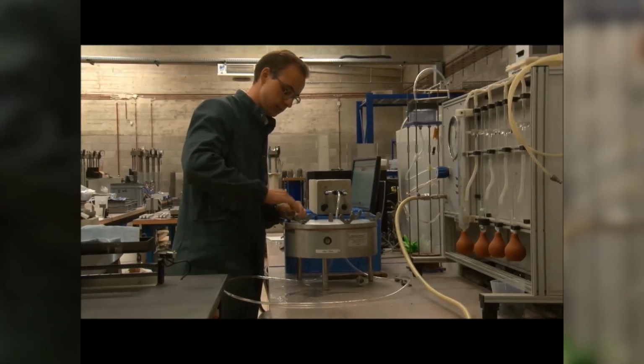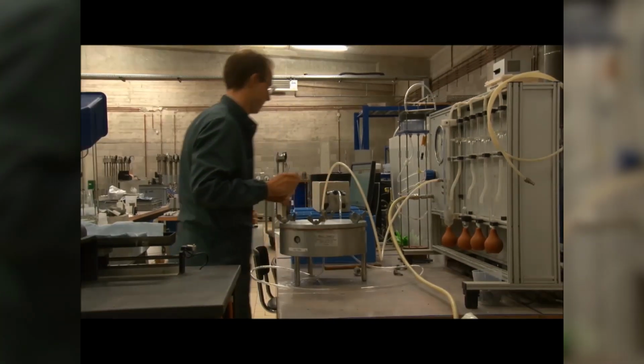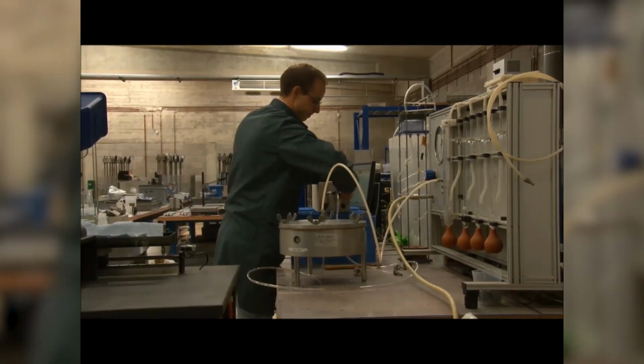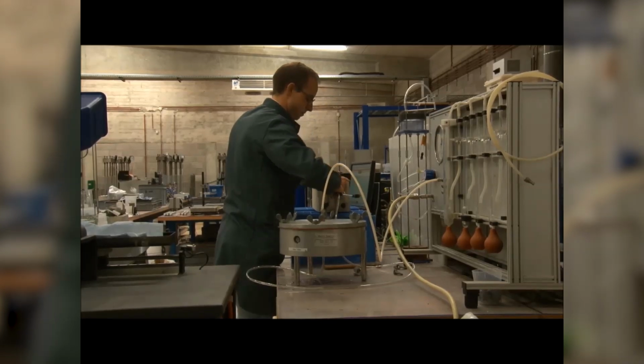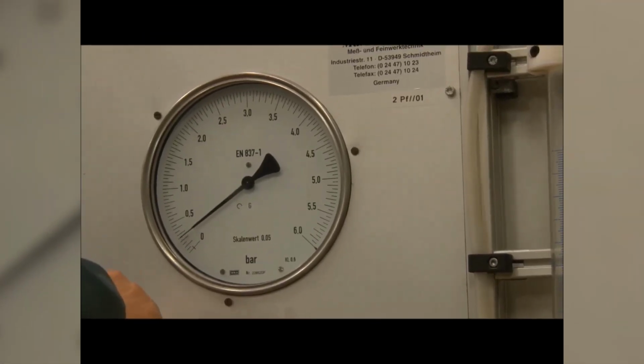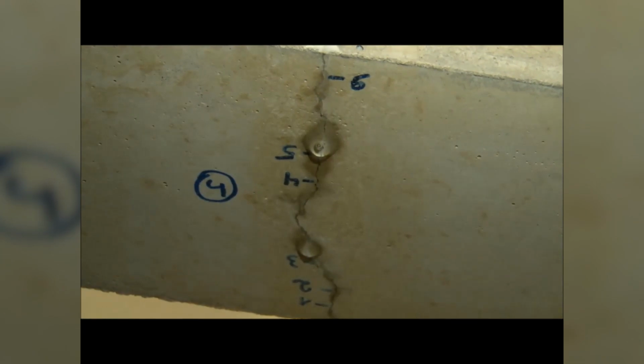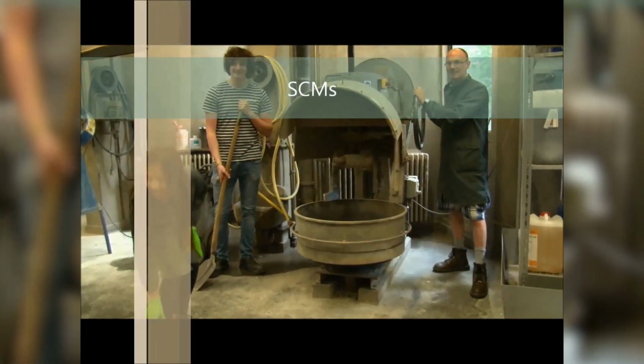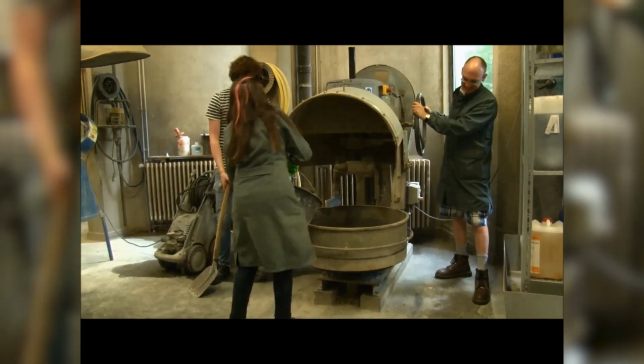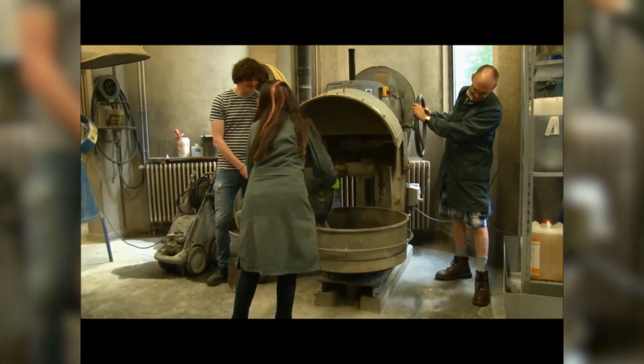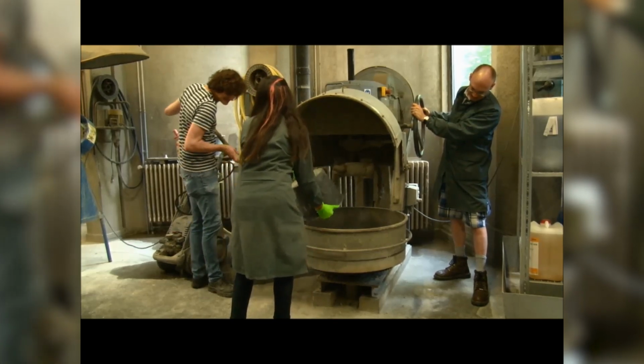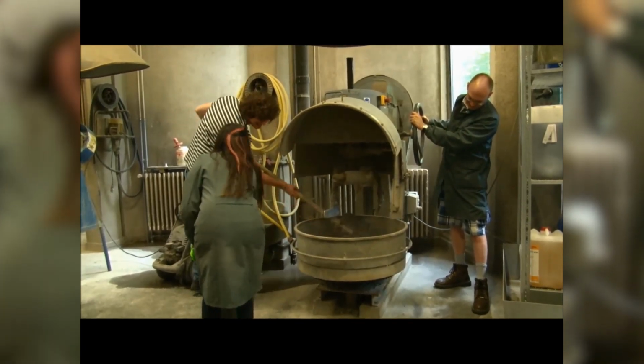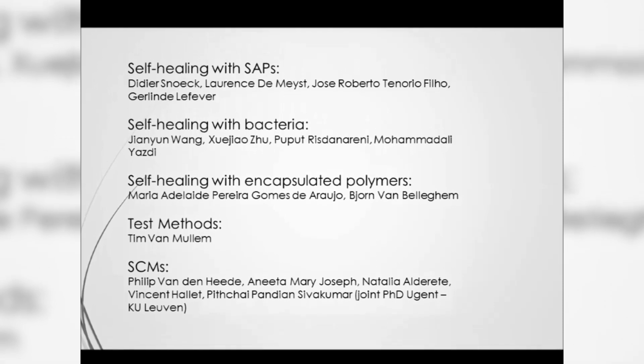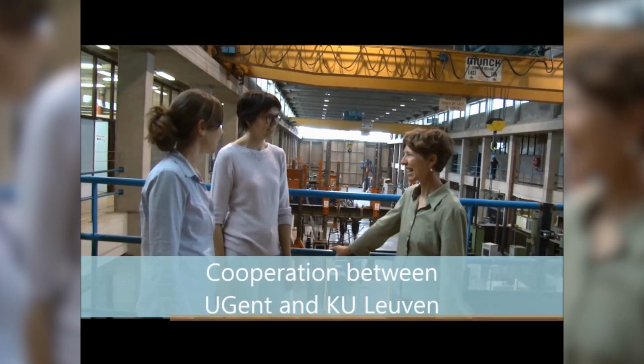It's well known that for every ton of ordinary Portland cement produced, around 1 ton of CO2 is emitted into the atmosphere. To reduce cement-related greenhouse gas emissions, part of the cement could be replaced with byproducts from other industries that also have cementitious properties. For example, pozzolanic fly ash from coal-fired electric power plants, pre-treated fine-ground bottom ash from municipal solid waste incineration, processed slags from the steel industry, etc. Concrete compositions with the incorporation of these materials count as potentially green concrete types, on the condition that their durability and service life performance in various environments remain adequate.